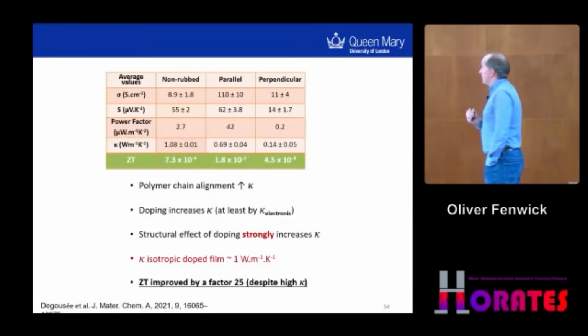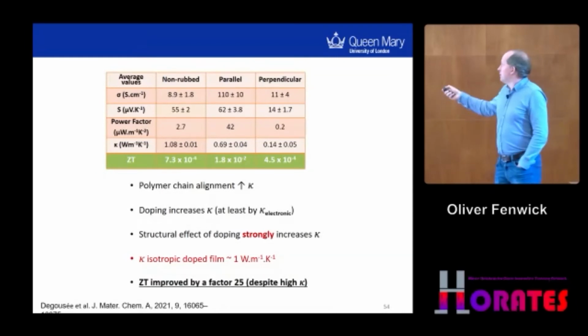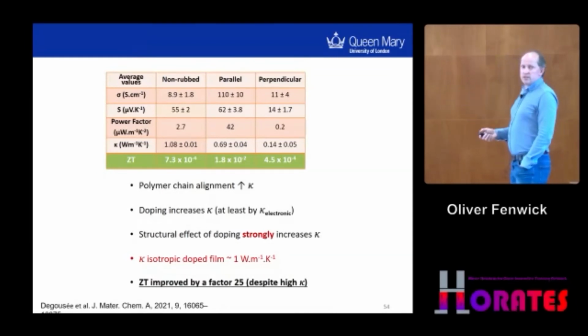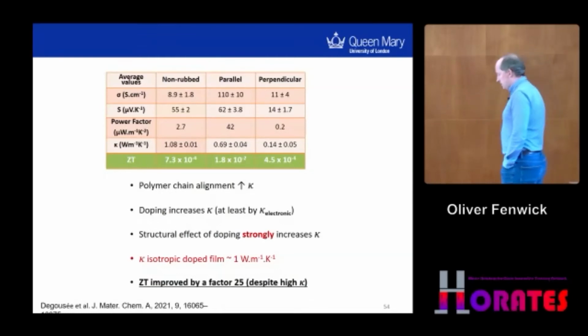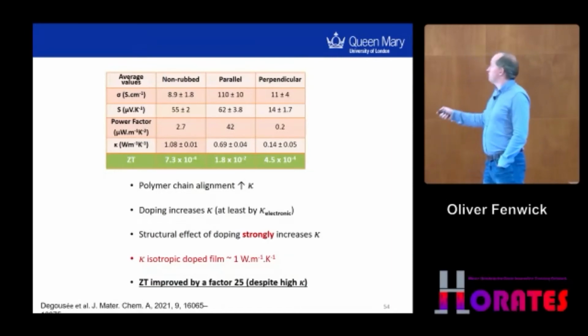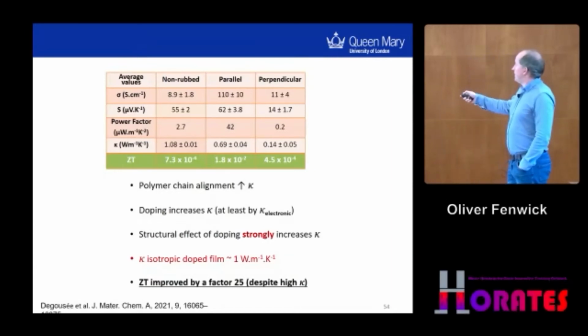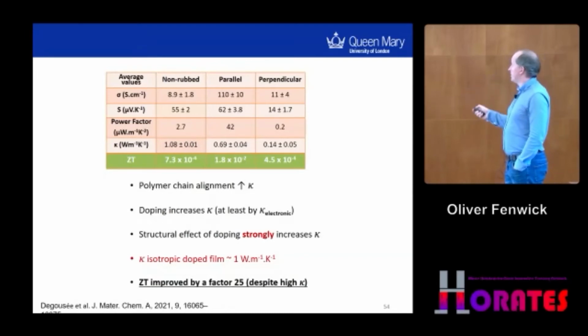Anyway, I think the take-home messages are that polymer chain alignment does increase thermal conductivity. Doping, in the case of P3HT, increases the thermal conductivity a lot, but it is a structural effect of the doping that can increase the thermal conductivity. And we can get thermal conductivities greater than 1 watt per meter Kelvin.